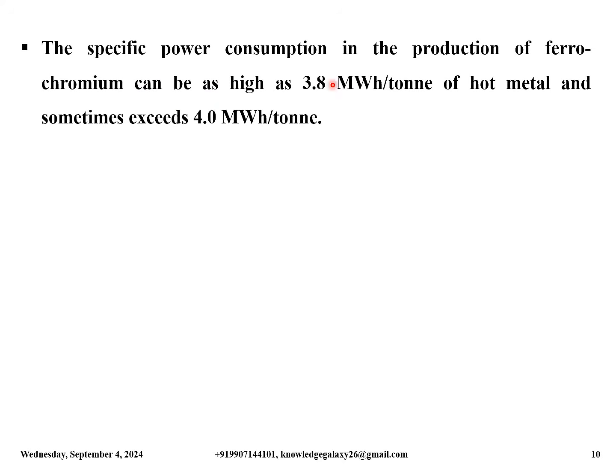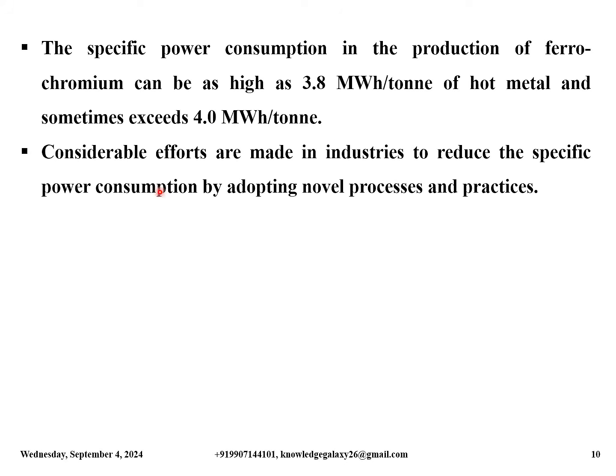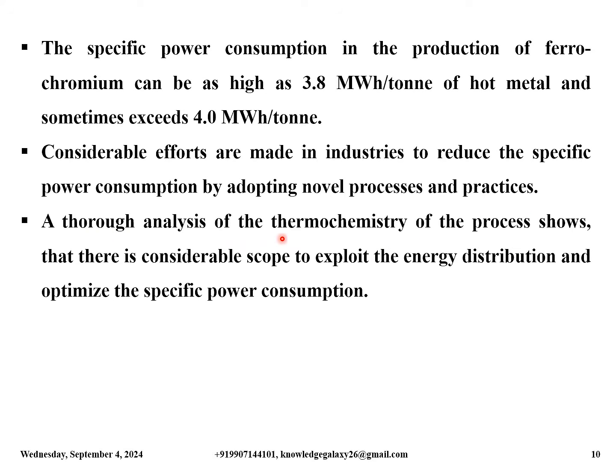The specific power consumption in the production of ferrochromium can be as high as 3.8 megawatt hour per ton of hot metal and sometimes exceeds 4 megawatt hour per ton. Considerable efforts are made in industries to reduce the specific power consumption by adopting novel processes and practices. A thorough analysis of the thermochemistry of the process shows that there is considerable scope to exploit the energy distribution and optimize the specific power consumption.